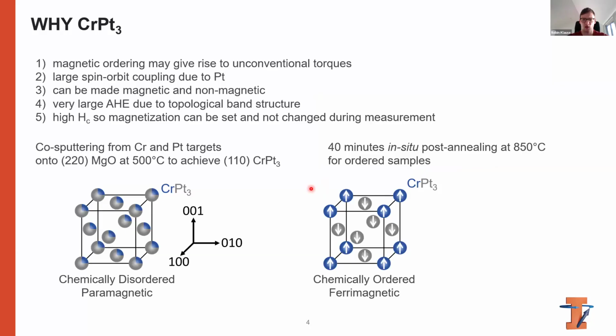I'm not completely sure why that is exactly the case. I would assume that 500 degrees is not quite enough energy for the atoms to arrange themselves in the ordered phase, and that 850 degrees is more suitable for that. I've worked on another material which is kind of different, manganese 3 platinum, which also needs relatively high temperature to grow a very nice ordered crystal structure. So I don't know exactly the reason behind it, but that's what we see in this case.